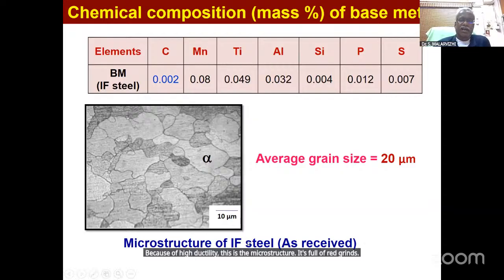Why is it called interstitial free steel? Because carbon is almost 0.002. If it becomes 0, it is iron, because we need to keep some carbon. So one of the interstitial elements is carbon, and it is kept close to 0, 0.002. And this is the microstructure. Average grain size is only 20 microns.